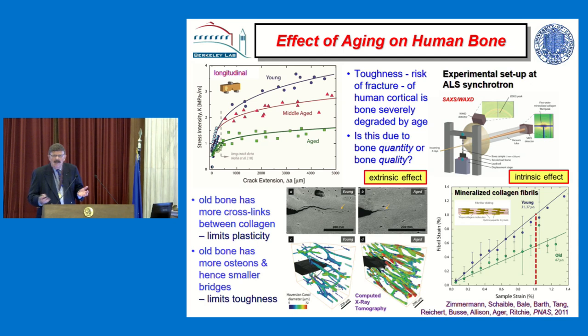All this is human bone. And you can see there's a vast reduction in the toughness for the cracks to grow. So what causes that? Well, again, this is a biological material. It has intrinsic and extrinsic toughening. The extrinsic toughening is a little difficult to see here, but you can see these little cracks that form parallel to the main crack.